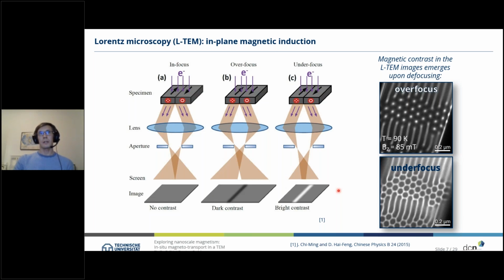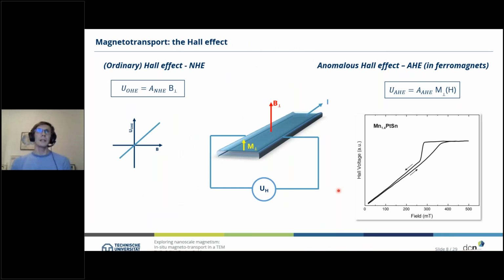This is one technique we want to use to image the magnetic structure of the sample, which is sensitive to the in-plane magnetic induction. On the other hand, we want to use the so-called Hall effect, which is shown here as a sketch in the center. So we have our magnetic sample, or a sample in general, which we contact with at least 4 contacts. 2 we use to run a current through the sample, here from bottom to top. And perpendicular to that, we will measure with 2 contacts the so-called Hall voltage. And then we can apply a magnetic field perpendicular to the current direction.